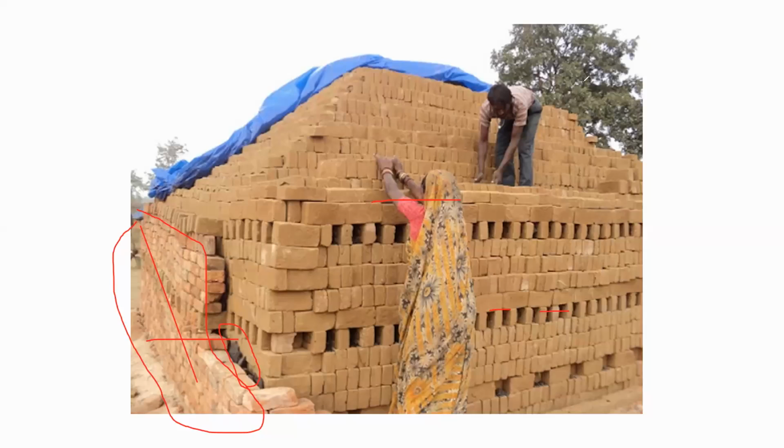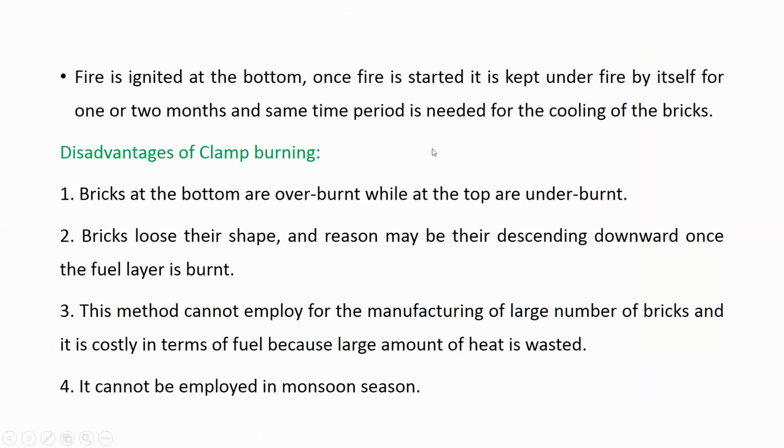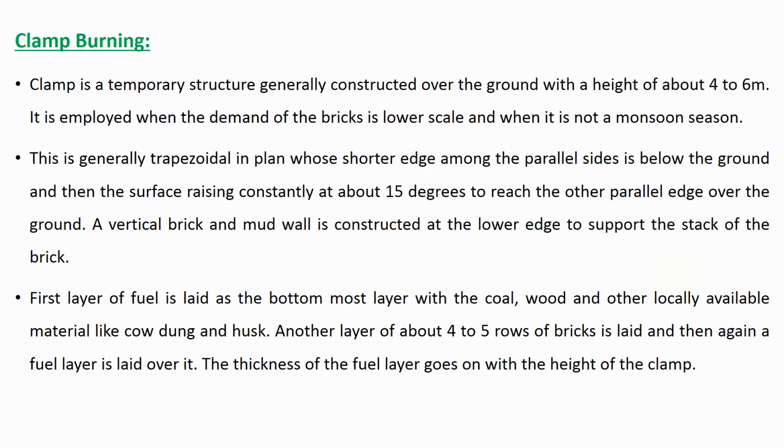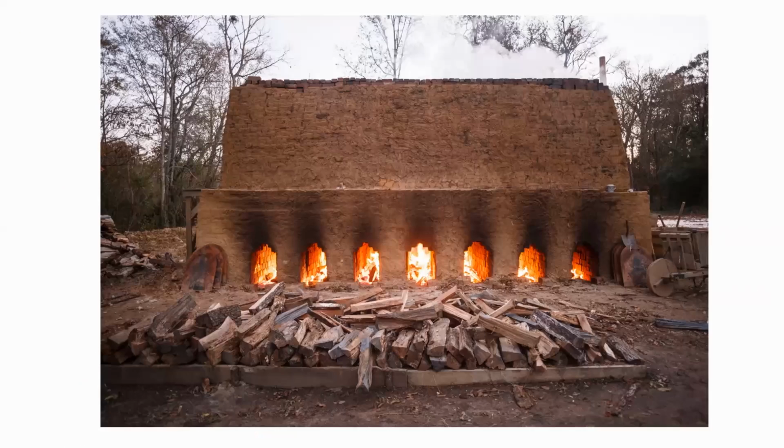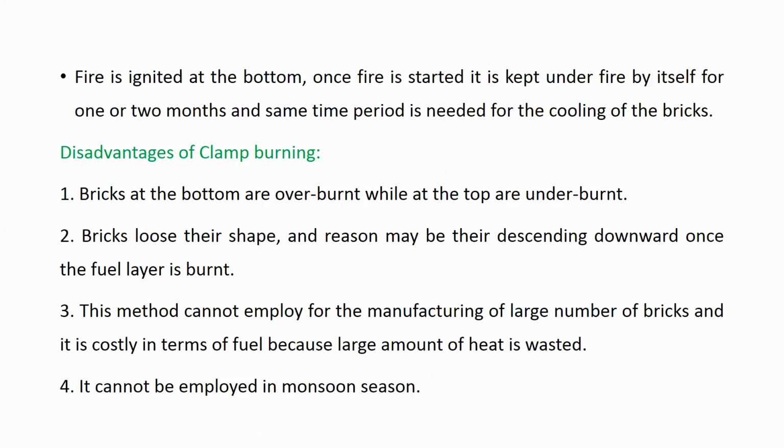Okay. So this is about clamp burning. Next, fire is ignited at the bottom. Once the fire is started, it is kept under the fire by itself for 1 or 2 months, and same period is needed for cooling of the brick.